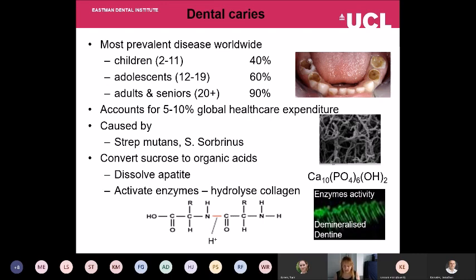It's caused by bacteria, specific bacteria like Strep mutans and sobrinus, which convert sucrose from food into organic acids. What these do is they chelate the calcium and dissolve the phosphate and hydroxyl groups that are in the apatite that's in both the surface enamel and the underlying dentine. What then happens is once the dentine is demineralised, you get enzymes being activated that hydrolyse the remaining collagen.